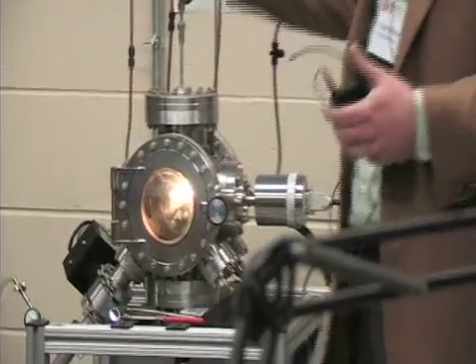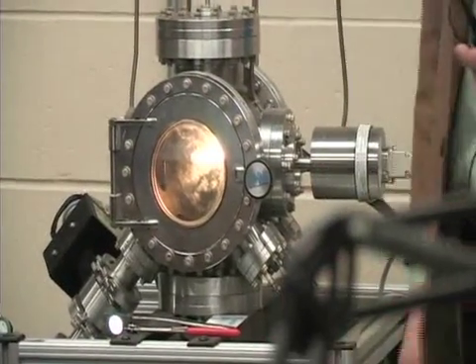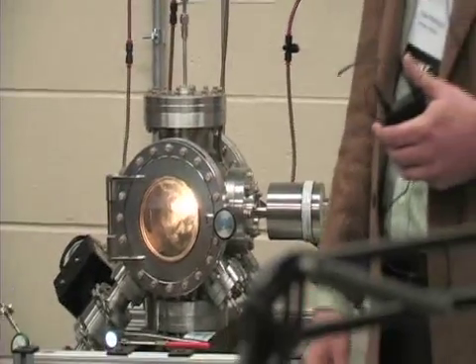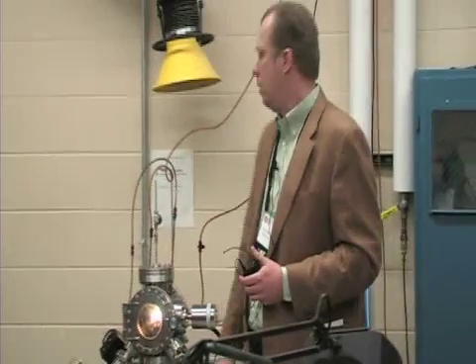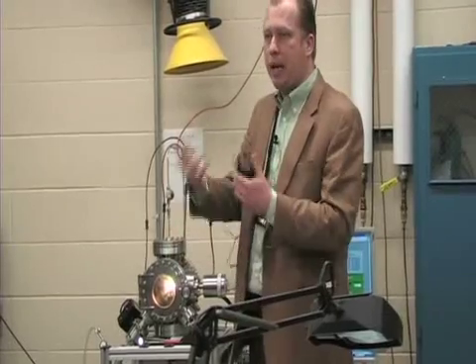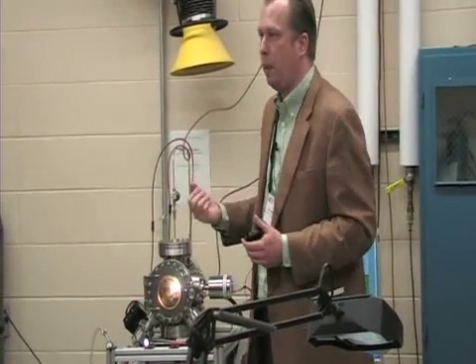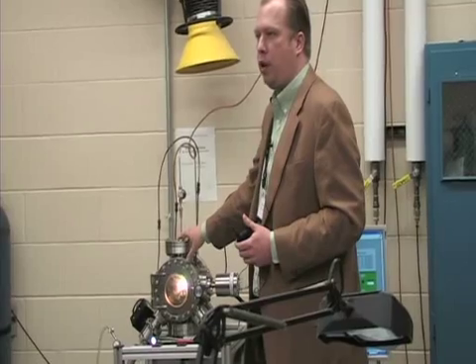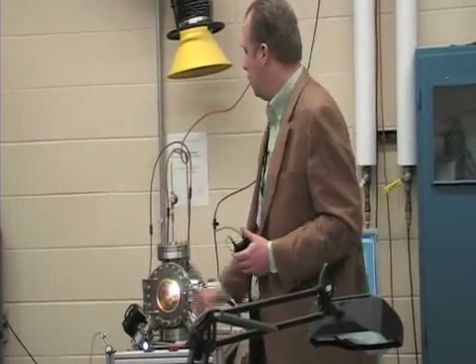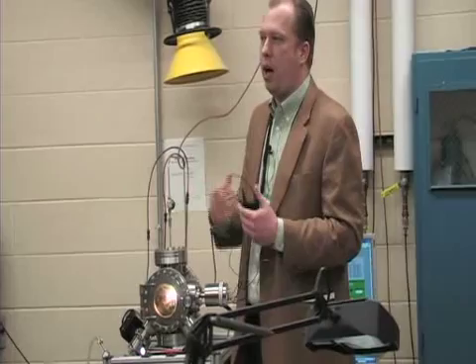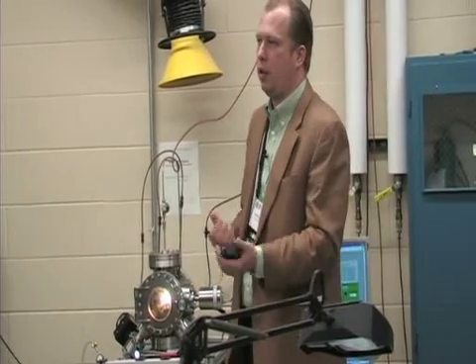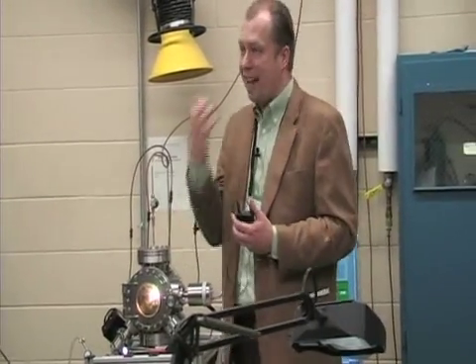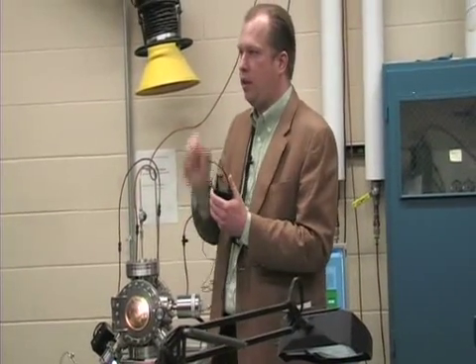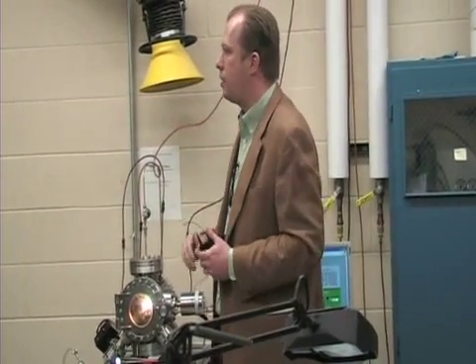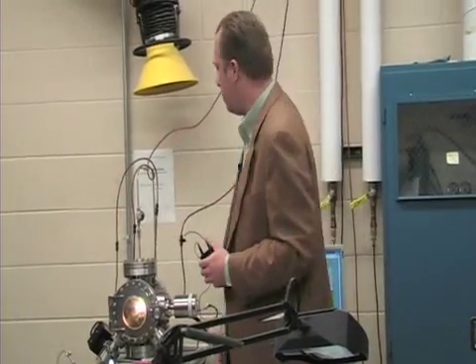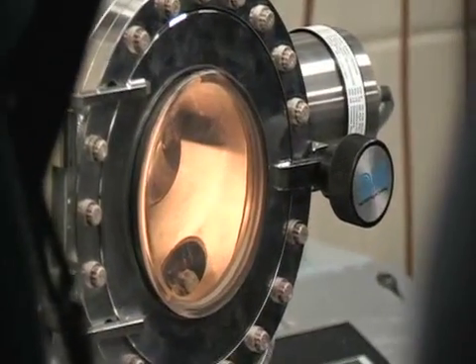Tungsten filaments, just like the old light bulbs here, we get them to about 2,000 degrees Celsius to dissociate those gases. All right. And the radiation from them heats the substrate, in this case a micro end mill, and then the gases come down under the right pressure and gas mixture conditions. When they hit the hot surface, chemical reactions occur, and ultimately what we're looking for are diamond bonds forming. So literally it is an atom by atom process of synthesizing or growing this diamond film on the coating.